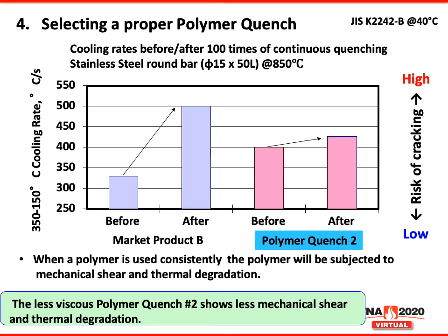Now here what we did is we heat treated the stainless steel round bar. And what we did is we used 50 milliliters of polymer and a diameter of 15 millimeters and length of 50 millimeters. And we used two different polymer quenches. Again, the difference is in the viscosity. The shorter the polymer chain, the less viscous the polymer is, and you show less mechanical shear and thermal degradation by shortening the polymer chain length.